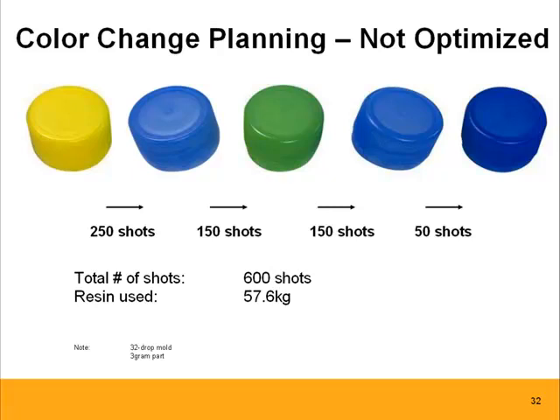And I'll give you a quick demonstration here in regards to the impact of a not optimized color change versus potentially optimized. So in this case, we're changing colors between the yellow and the blue and the green and the blue and the darker ones. A total, let's say this would all have happened in a given day, we would need 600 shots, or for this 32 drop mold with a 3 gram part, 57.6 kilograms of material in a given day.